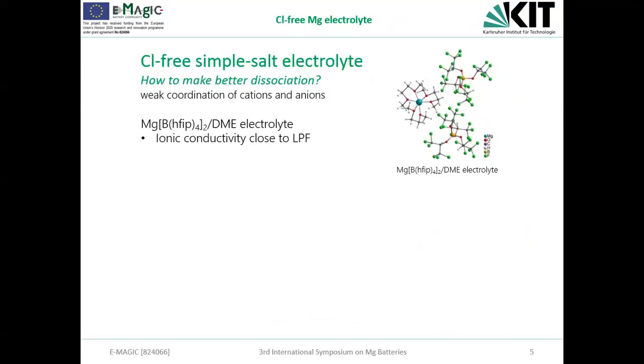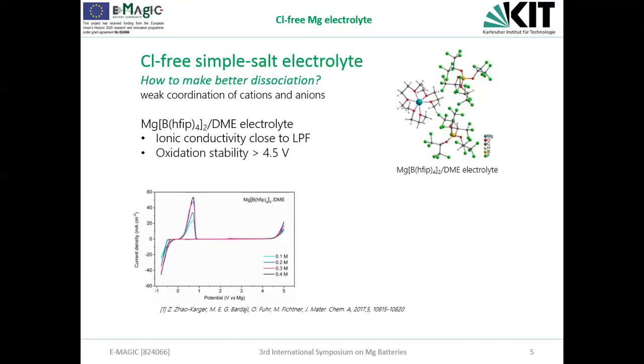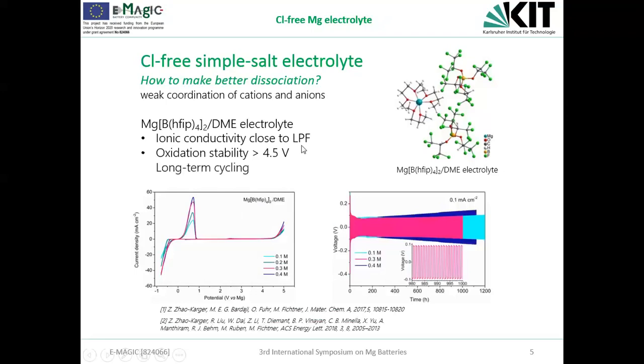And we also work in this direction and developed an electrolyte of such kind. And here is the structure of this electrolyte. Basically, we have a large anion, which contains a boron center and fluorinated alcohol ligands, and this makes a weak coordination between the anion and the cations, which also means we have better dissociation and higher ionic conductivity in the electrolyte solution. So from the CV, we see we have even higher oxidation stability of up to 4.5 volts against platinum. And we have very efficient magnesium stripping and plating, as shown in the reduction and oxidation peaks. So the long-term cycling is also good.